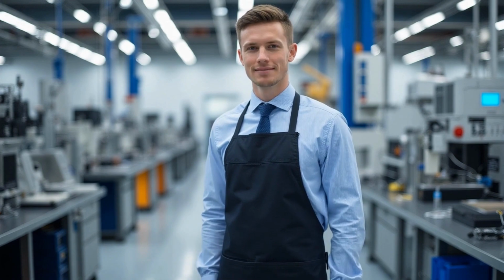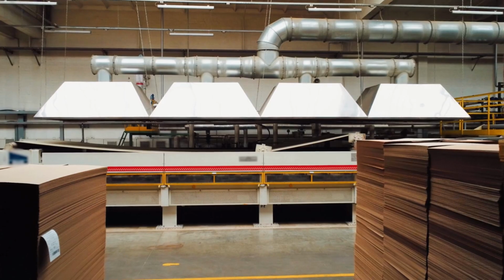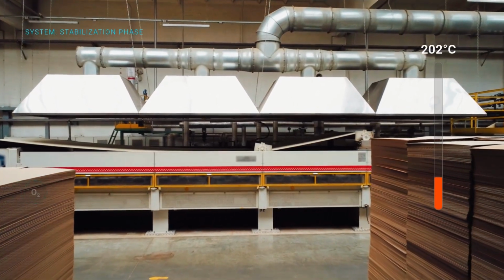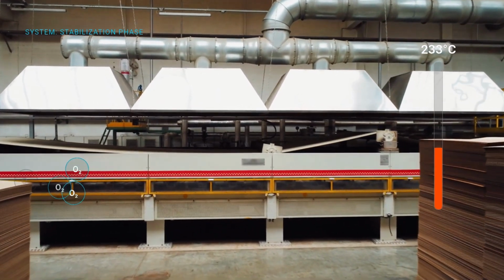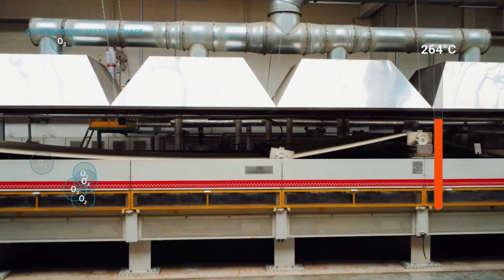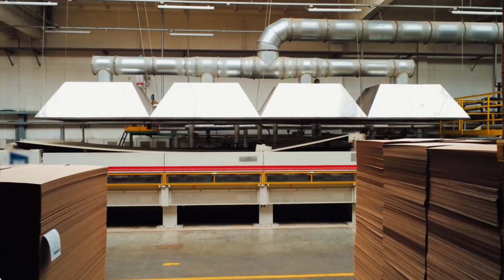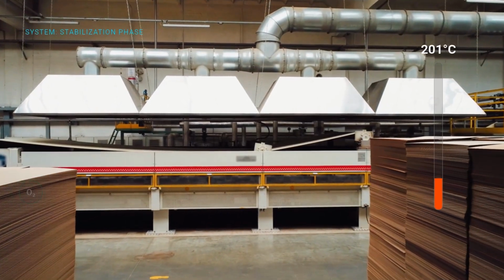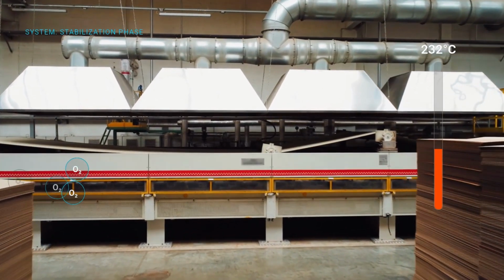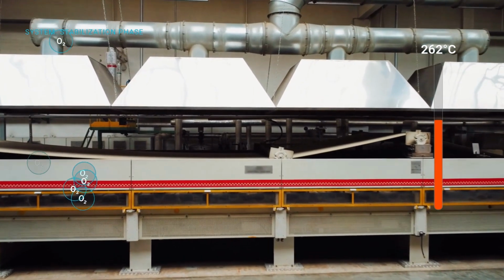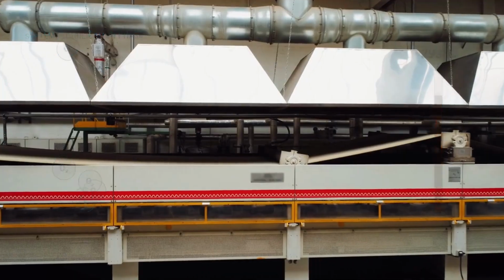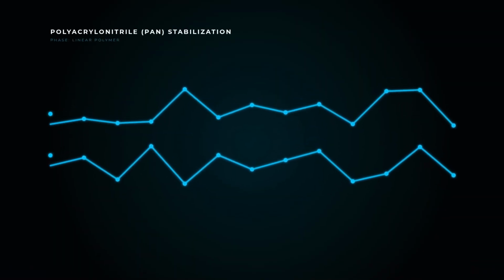Now the torture begins. We have to lock its structure. If we put this white fiber straight into a 2000-degree furnace, it would instantly melt. Before carbonization, we must lock its structure in place. The fibers are fed through ovens running between 200 and 300 degrees Celsius. But here is the critical trick. The fiber is kept under immense physical tension. As the heat rises, the chemistry fundamentally changes.